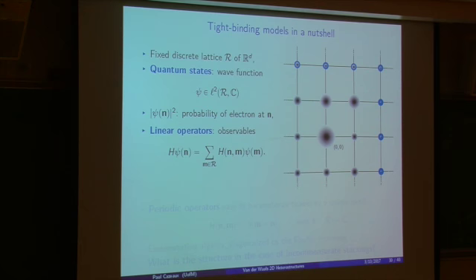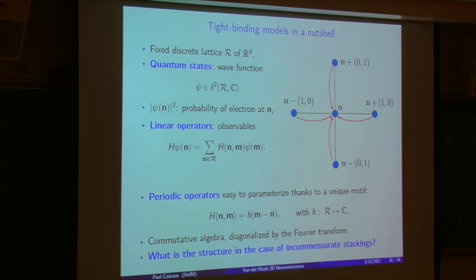In a general case, this is very hard to parameterize, but in the periodic case, it's very easy to look at these kinds of systems, because the only thing that is important is the difference in positions of two atoms, because everywhere is the same. Therefore, a given coefficient of this matrix can be parameterized by the vector between the two points. In particular, the simplest tight binding model we can think about, for example the Harper model, will include only nearest neighbor interactions. So this coefficient here will be 1 for such pairs of sites.